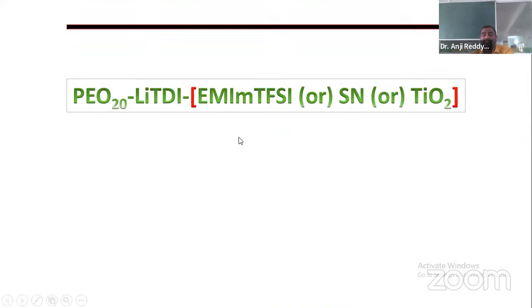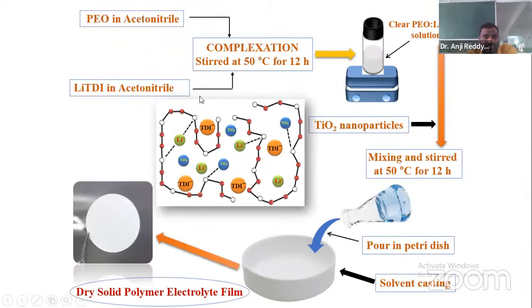And LiTDI we have also studied, with ionic liquid and succinonitrile plus nanoparticle TiO2. We compare all these to see which one is good. This is our synthesis mechanism. This is PEO and lithium salt. We dissolve both in acetonitrile and stir for 12 hours at 50 degrees centigrade. After getting a homogeneous solution, we add TiO2 nanoparticle or succinonitrile plus or EMImTFSI ionic liquid. Again we stir up to 12 hours at 50 degrees centigrade.